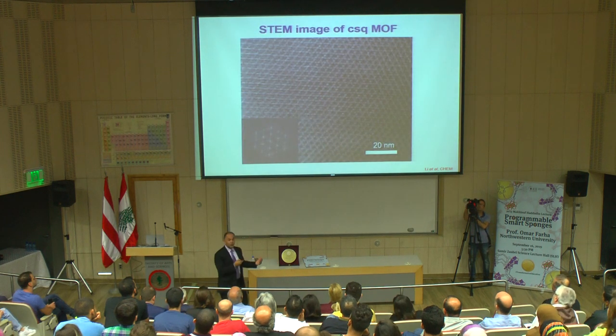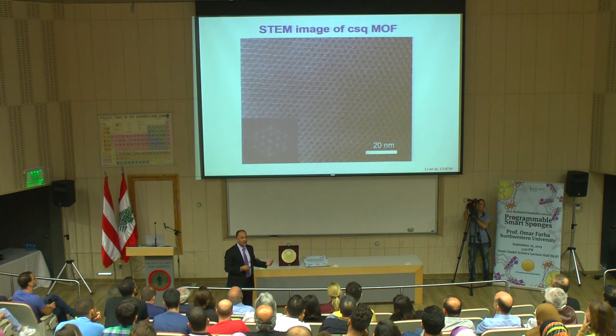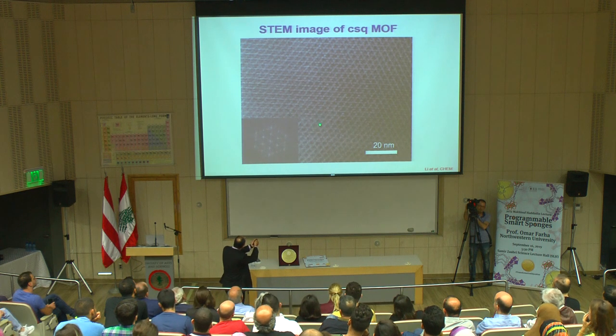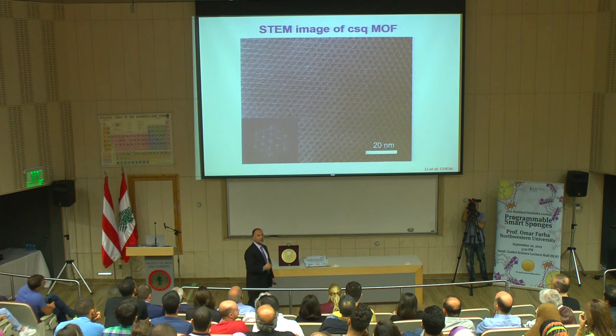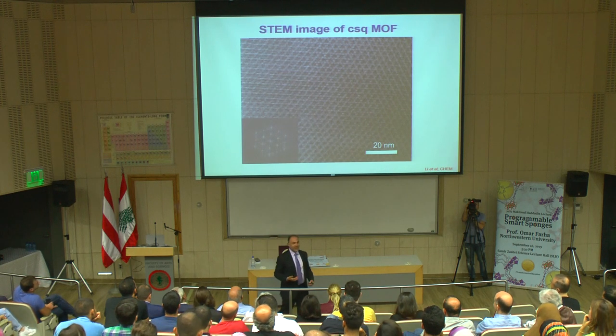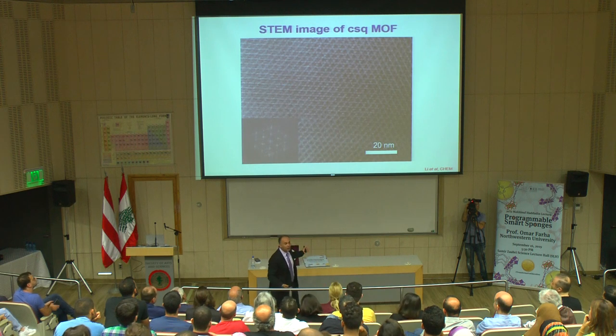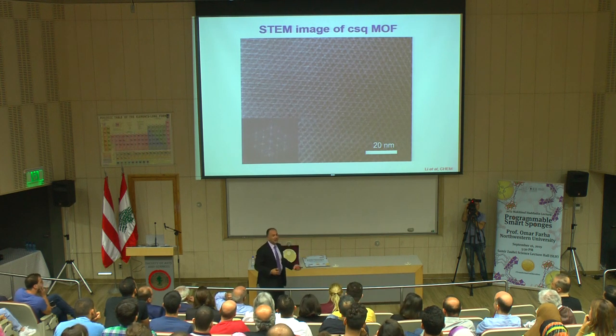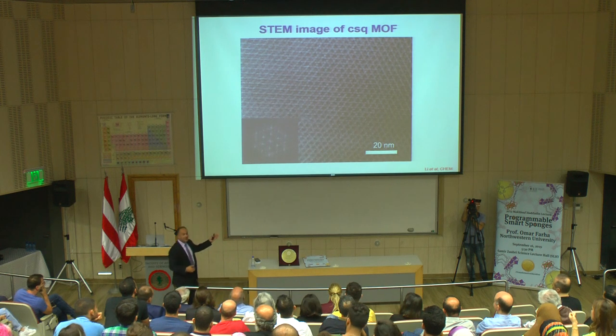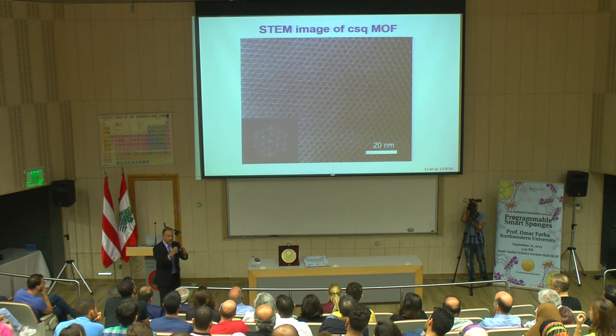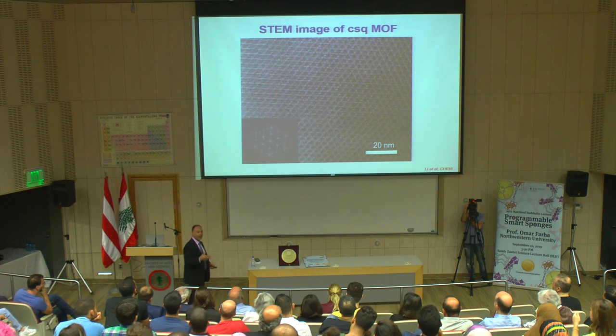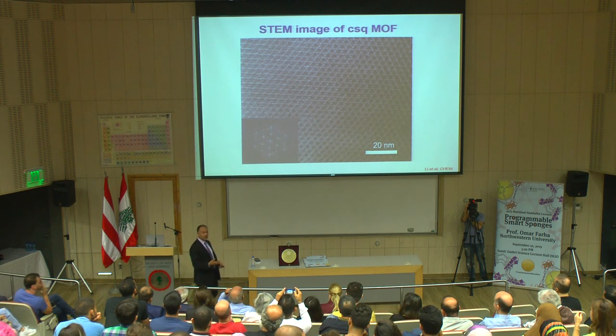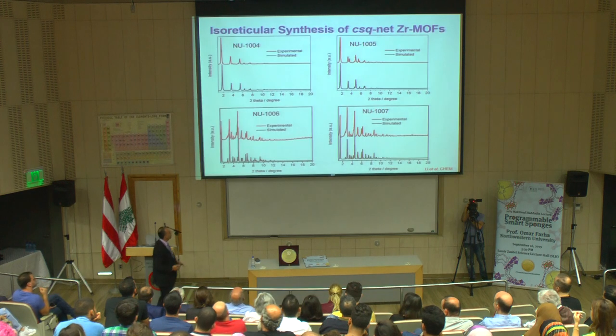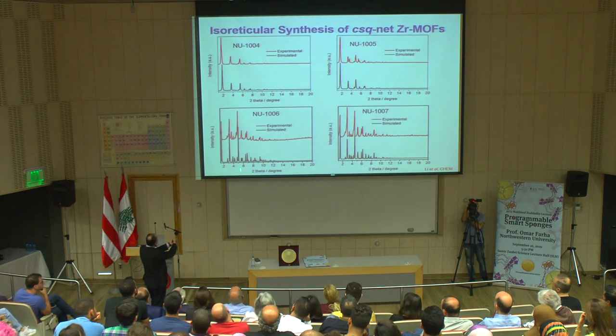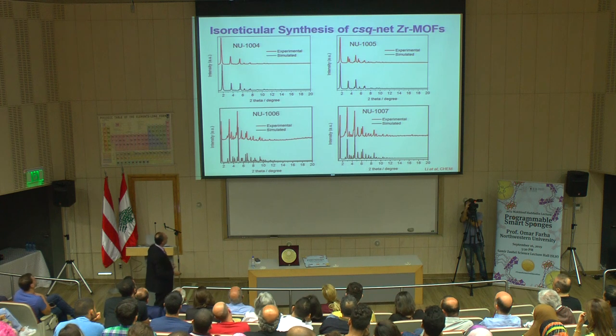We could even now do STEM to see that we made the right topology, and you could see this is the triangle, and that's the hexagon. A few years ago, unless you have K3 or K2 cameras, you would burn those organics using STEM. But now we could see even the cluster of those zirconiums and see exactly the structure down to the nano regime. With the crystal structure, we could go down to the angstrom level. And that's what we did. We could match that our bulk matches our single crystals.